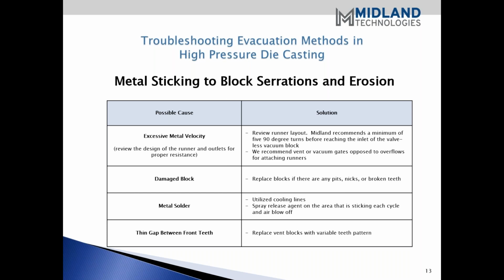As far as the solder goes, utilizing cooling lines in the blocks to minimize that too. And then again, I mentioned spray. The reality is that spray is primarily used in most die casters as a means of assisting cooling of the cavity or cooling of an area specifically. And in this instance, we're not worried about making a pretty looking vacuum serrated pattern after we leave the casting. So in this instance, if you spray it properly and blow off, you're going to minimize that problem.